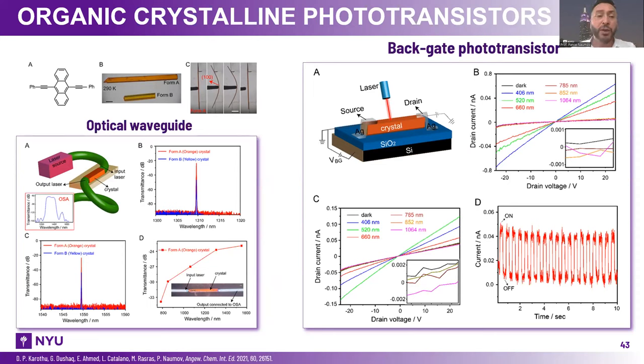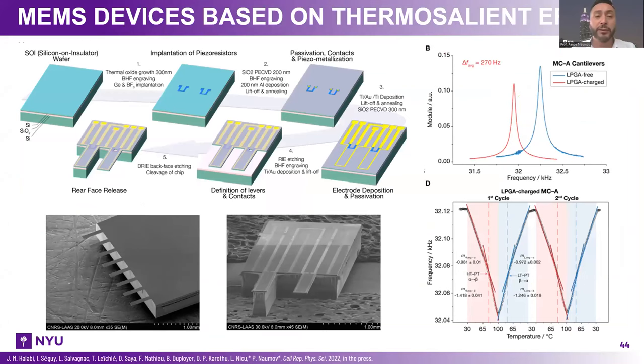This is another case of a microelectromechanical device, or MEMS device, where we have a crystal deposited on cantilevers and these oscillate at a certain frequency. When we heat this device, we can take the thermosalient crystal over a phase transition, and what happens is we change the frequency of oscillation. So in principle, we control the frequency at which this device is operating, and this can have implications on the performance of the device. As you can see clearly, we have different frequencies for different temperatures.